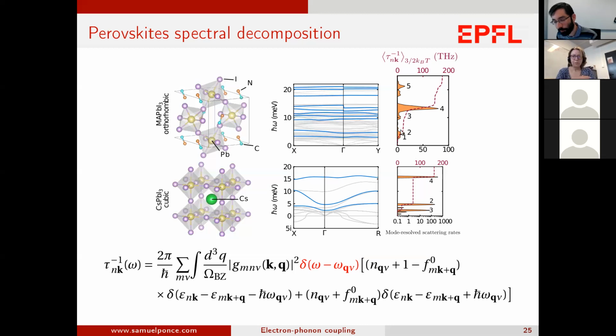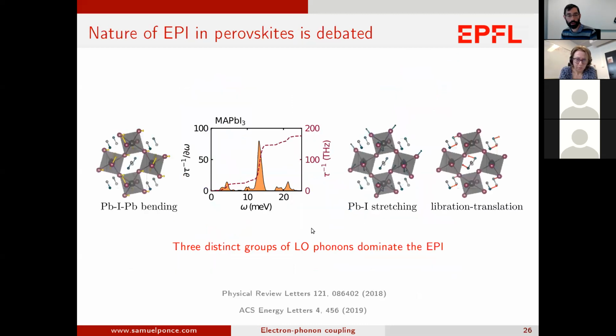So 3 was the minimum number we needed to reproduce the ab-initio data in the case of MAPI orthorhombic. And in that case, we take the average of 1 and 2, if you want. In cesium lead iodide, you have 2, which is more or less this one, and then you have a small one, which corresponds to the low one. This one here corresponds to this bending, but there is also one that I'm not showing here, the third one, which corresponds to another motion. I think it's maybe rocking, not super sure.